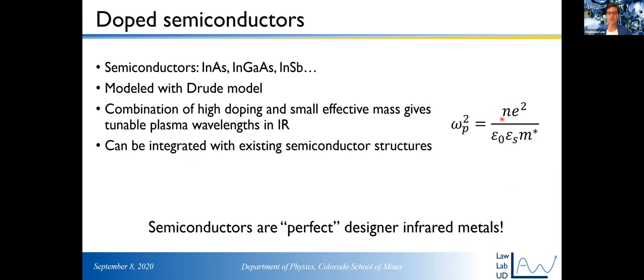because we can control the doping of a semiconductor. I'm not going to go into the details here. I'm happy to talk about growth for hours and hours and hours. But the idea here is, if I'm growing indium arsenide, indium's a group 3 and arsenic's a group 5, right? So 3 plus 5 is 8. So all the bonds are satisfied. But you can add a little bit of silicon. Silicon's a group 4. Turns out that silicon prefers to sit on the indium site. So the silicon is only using 3 electrons for bonding. So it has 1 electron left over. And that electron is basically a free electron donated to the indium arsenide. So by choosing how much silicon we dope in, we can change this doping density and we can control the optical properties of these materials.